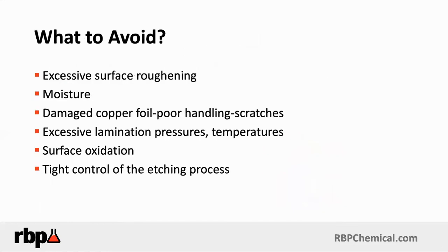So, to get good adhesion, what do we need to do? First of all, we don't want resist lifting. We want good conformance. It's about the resist conforming to the laminate surface and holding there during the various operations. We do want to avoid things like oxidation, poor rinsing, moisture, any handling issues, because scratching the copper foil, damaging it, scratching it, bending it, that's all going to potentially add into the equation for poor resist adhesion. In a future session, we'll talk about the lamination pressures and temperatures. But again, short story here, excessive lamination pressures and temperatures, and of course, too long of a hold time between lamination and exposure can all lead to lack of adhesion of the photoresist to the surface.